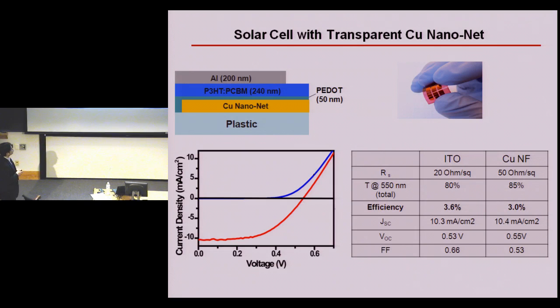So this is a quick demonstration of using this transparent copper nanofiber as an effective transparent electrode for plastic solar cells. So this is the device structure. We use P3HT:PCBM as the active layer for this solar cell fabrication. You can see here that the main message is the power conversion efficiency is 3.0%, very comparable to the ITO-based devices. But remember, the process as well as the materials are all optimized for ITO-based devices. So I think with further development and optimization, we can further enhance the power conversion efficiency.